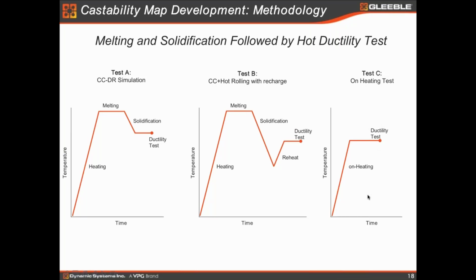But here the right one, why will people think, why do you need to do this test? That is very important, because for every this kind of testing, where we are doing the controlled casting, solidification, and hot ductility, you need to have base results or reference results. So we call this test the on-heating test, which means you cut a sample out of a deformed structure, either rolled or forged, and you heat it to whatever temperature range that you want to study, the casting temperature range and the rolling temperature range. You do the same temperature range hot ductility test as you want to see, simulating either the CCDR or CC reheating.